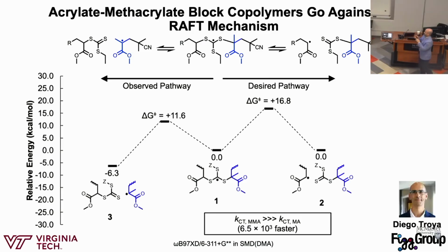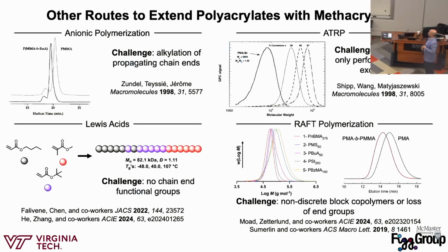So essentially, you can't chain extend a less activated monomer with a more activated monomer in RAFT polymerization because the kinetics and the thermodynamics are fighting against you. So it just doesn't work, right? That just is not a thing that works. You really have to think about a different way to overcome this process, which we're relying on to actually give us control of the polymerization. So it's really challenging, and it's a problem that's persisted in RAFT polymerization since its inception.